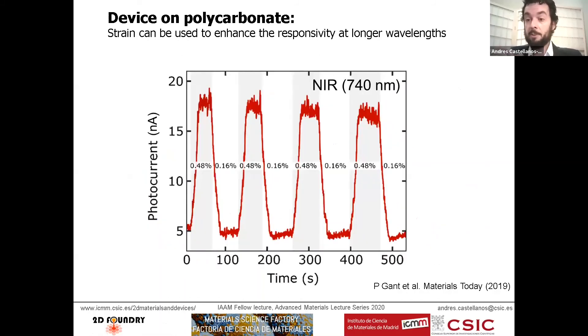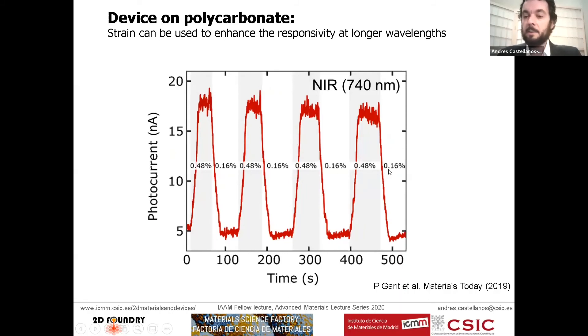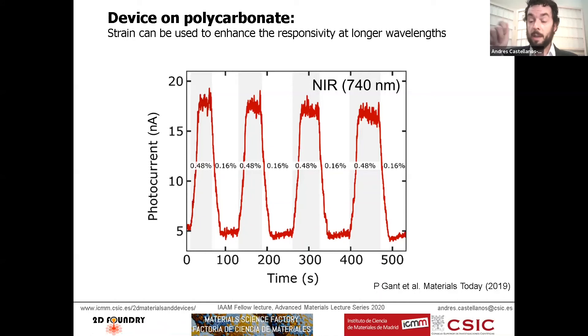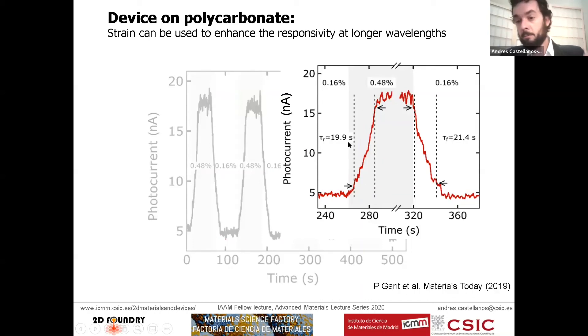Using our temperature stage, we can change the level of strain in time. For example, we modulate the strain back and forth between 0.48 and 0.16 percent repeatedly using molybdenum disulfide straintronic devices — demonstrating strain as a tuning knob indeed. We can extract the time response of our devices from these plots and obtain time responses on the order of 20 seconds, which in this case is limited by the thermal properties of our temperature stage, not something intrinsic to the straintronic device itself.